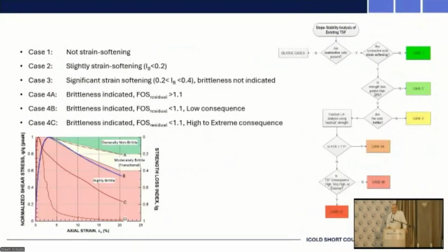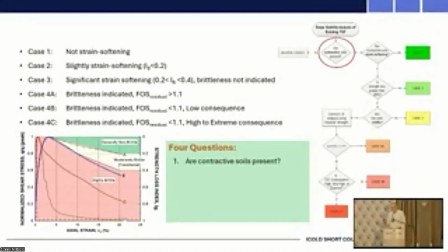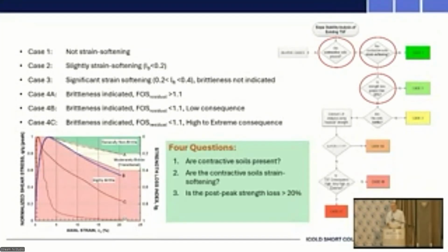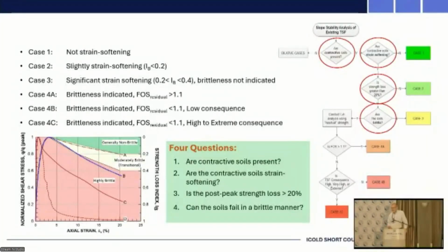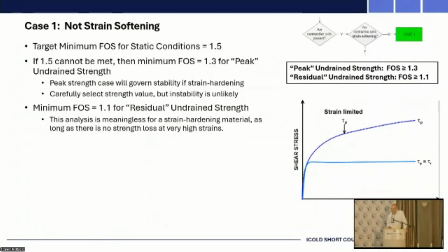We apply this framework to the flow chart. The flow chart revolves around 4 questions that lead to one of 6 outcomes. We have 4 cases depending on the type of behavior, and the 4th case, the highly brittle materials, is subdivided depending on whether the factor of safety is met and whether there's a potential loss of life. The 4 questions are: first, are contractive soils present? Secondly, are they subject to strain softening? If so, does the post-peak strength loss exceed 20%? And finally, can the soils behave in a highly brittle manner? Based on those, you have these different outcomes. I'll walk through those as quickly as I can, and I'll try to stay within the 25 minutes that I said I would.